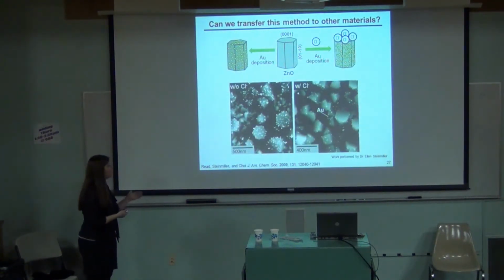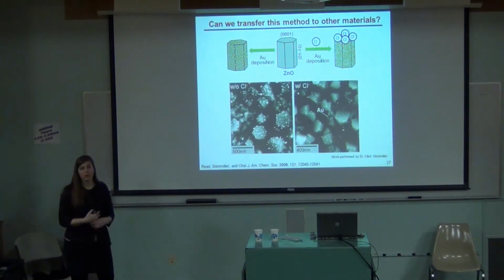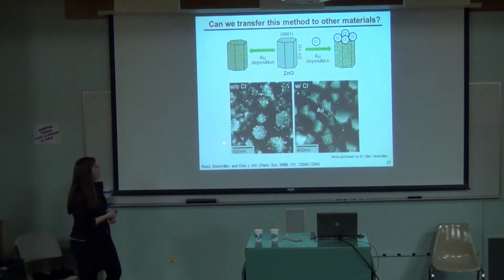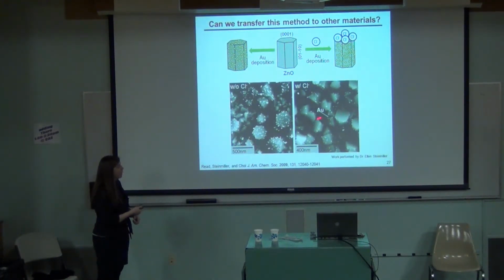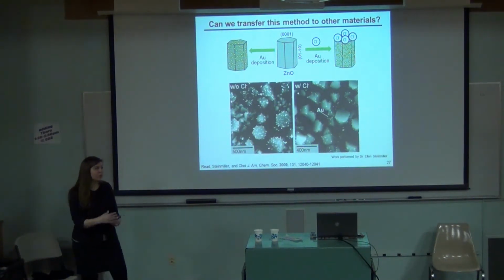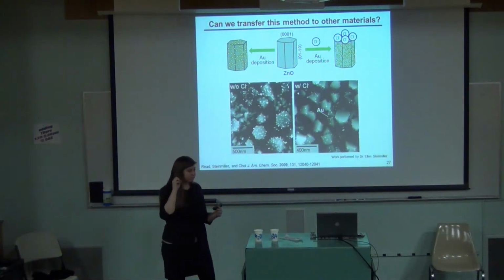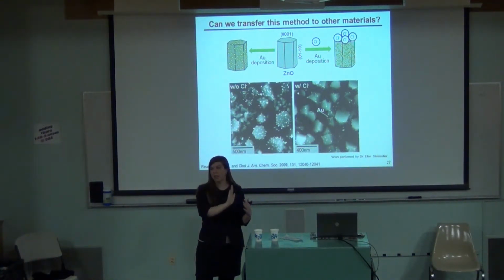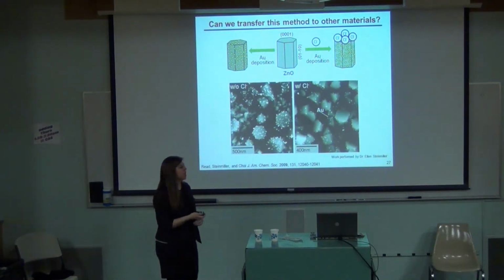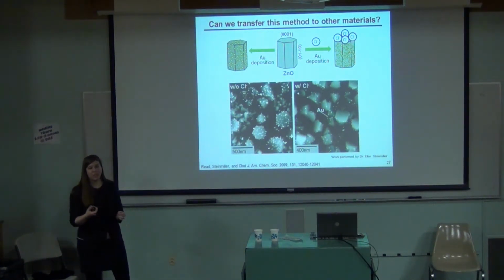And so then I told this to my lab mate, and hers was selectively blocked with chloride, so that's how she made her crystals. And so she tried it with chloride, and in fact, when you didn't have chloride, it went everywhere. But when you put chloride in her system, she didn't have anything at the tops of her crystals, which was beneficial because with light coming in, you want it to be able to hit the semiconductor surface, and you want it to be able to work with the catalysts that are on the planes of the crystal. So this was really a cool thing, and it also meant that other people could take my method and transfer it to other methods, and it's not just one way of doing something.